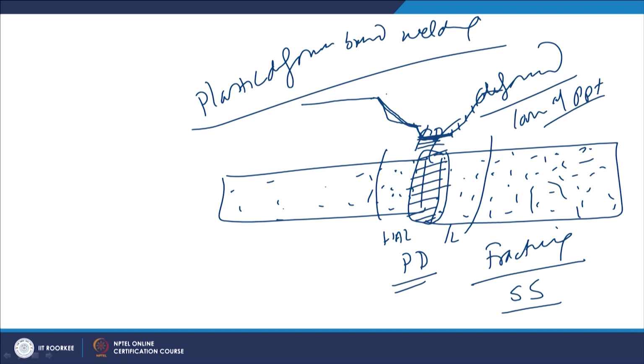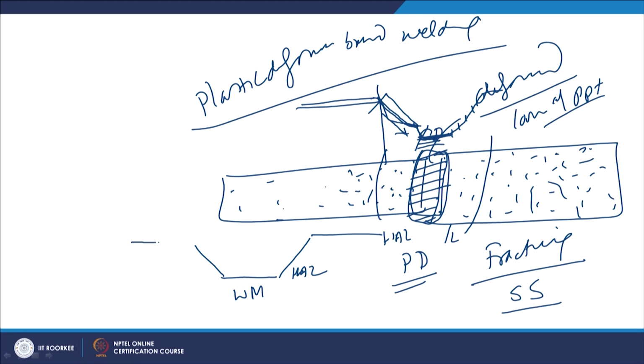So, wherever there is a gradient, that will be a zone where either an increasing or a decreasing amount of precipitates is present. The maximum precipitate density will be in the base metal, and then it will keep on decreasing gradually as we approach the weld metal, causing the gradual reduction in hardness. So, minimum hardness will be shown by the weld metal, then increasing hardness will be shown by the heat affected zone on both sides, and then the maximum hardness in the base metal.